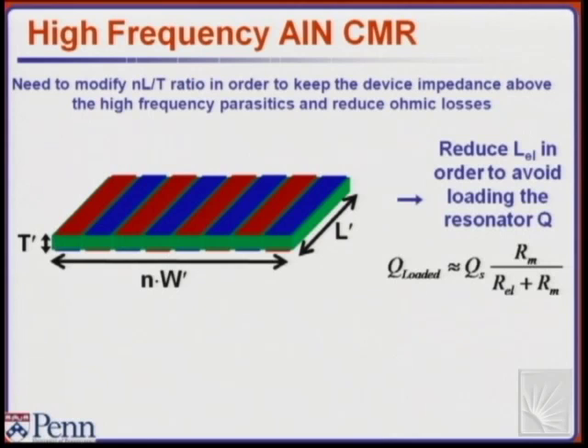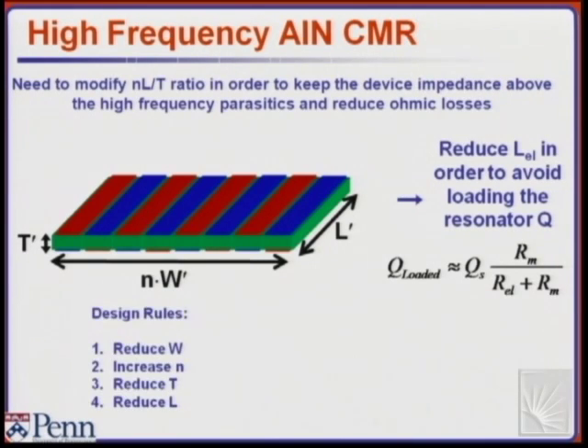And that is a problem because having very long electrode lines are actually killing your Q. Basically they're loading the quality factor of the resonator by introducing an additional resistance on top of the one of the device. The impedance of the device, the RM of the device goes down because you're making it thin. So you're improving the effective coupling, but the electrical resistance of the lines become bigger, so you're really effectively loading your Q. So you really need to make your device shorter.